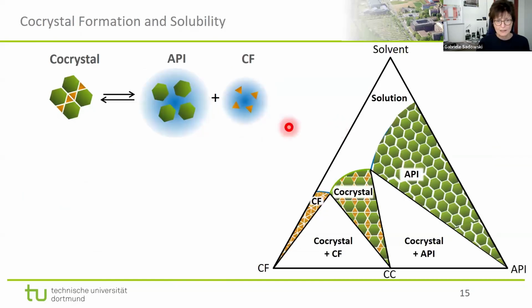So this brings me to co-crystals. What is a co-crystal? A co-crystal is a crystal that is built up of 2 different molecules. So we have an API, a pharmaceutical compound, and they very often have a very low solubility. Co-crystals are built of API molecules and co-former molecules, and they build a common crystal lattice. This crystal lattice is less stable than the one of the pure API, and so it will better dissolve. It has a higher solubility, but more importantly, it is faster dissolving.